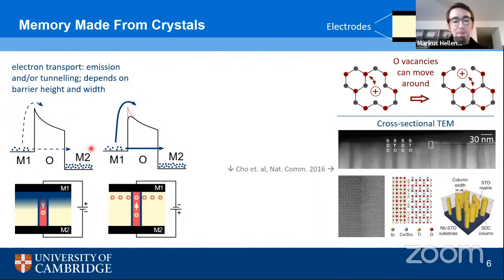But if we now apply a positive voltage to one of the electrodes, M2, for example, now because the oxygen vacancies are charged positively as well, the positive voltage at the electrode will drive them away and closer to the other electrode. But like I said, they are kind of confined to these pillars, so they cannot get out. And this means that they will accumulate at the interface to this other electrode. Now, the accumulation of positive charge at the interface means that the barrier that the electrons experience will be lowered,